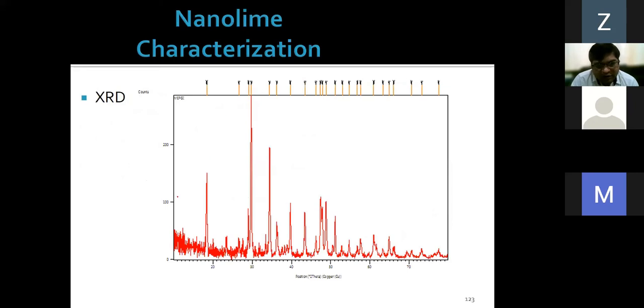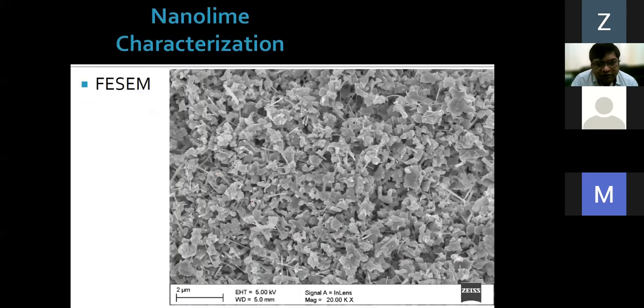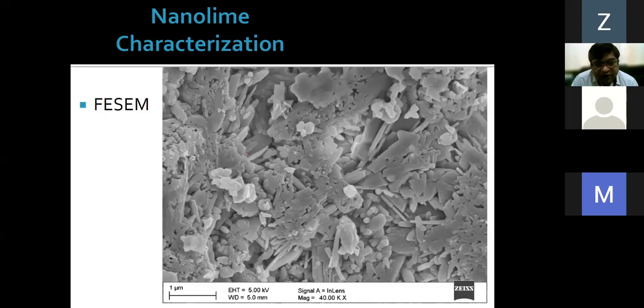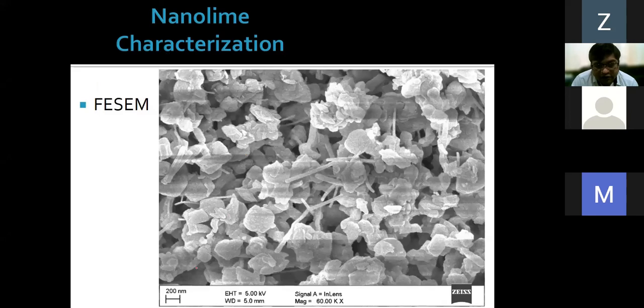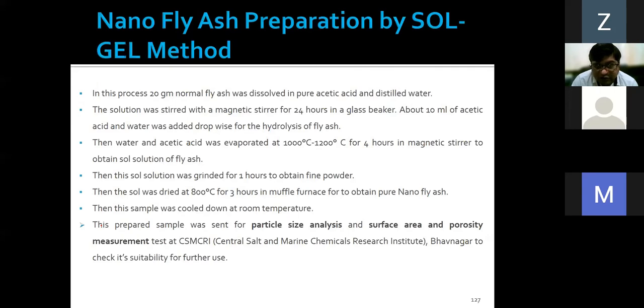I am not an expert in XRD and field emission microscopy, but I can at least tell you that whatever we manufactured in our lab was of the nano level. You can see the particle size is about 200 nanometer, in diameter and thickness, and there are some needle-like things. So that is a nano level of lime produced.